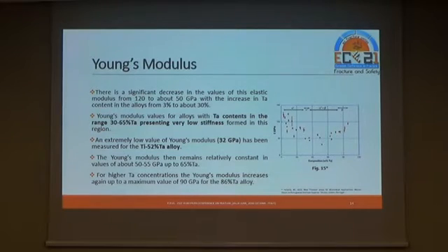Young's modulus characterization. There is a significant decrease in the values of this elastic modulus from 120 to about 50 gigapascal, with an increase in tantalum content in the alloys from 3% to about 30%, as can be seen in the figure. Young's modulus values for alloys with tantalum contents in the range of 30-65% present very low stiffness formed in this region.